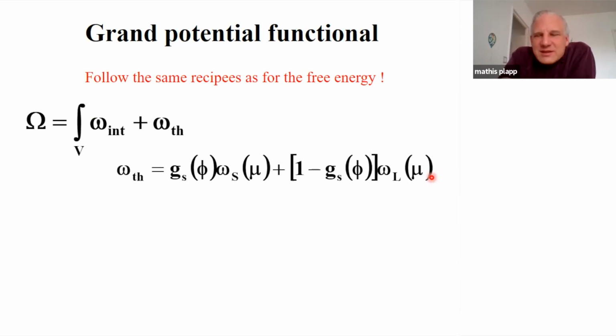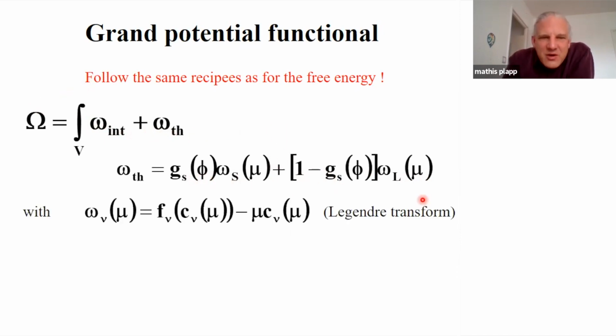Let's take the grand potential. So let's take the same stance that we did for the pure substance in the free energy. We separate the total thermodynamic potential, which is the grand potential, into an interfacial and a thermodynamic part. And for the thermodynamic part, we take a superposition between solid and liquid. Now, these functions omega of mu that appear here are the Legendre transforms of the free energy. So the free energy is a function of composition. For the Legendre transform, you calculate F minus mu C, and then you change variables from C to mu. So the resulting omega is a function only of the chemical potential. But you have to understand it in this sense: you take the free energy function, that is a function of C, but then you express C as a function of mu, and in this way, this becomes a function of mu.